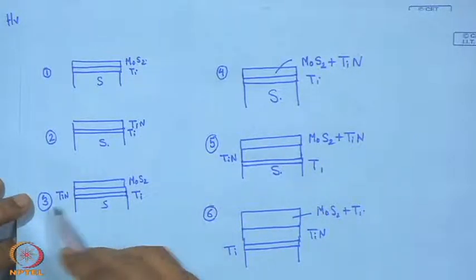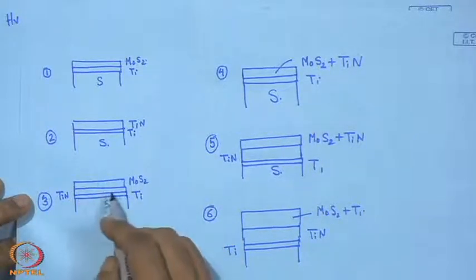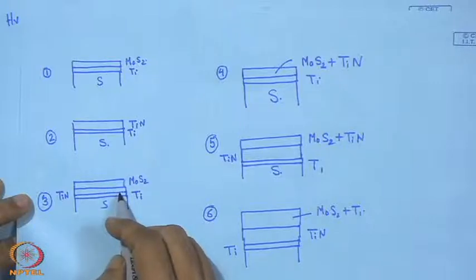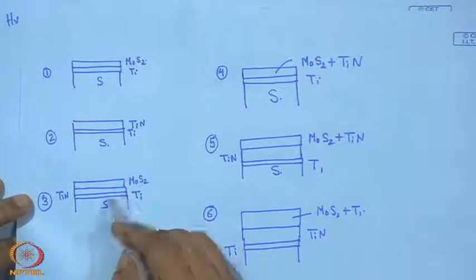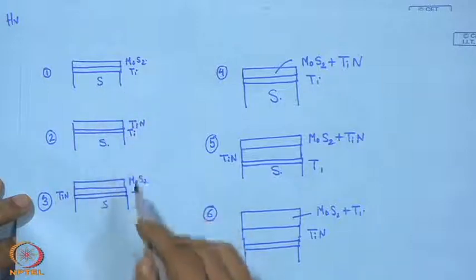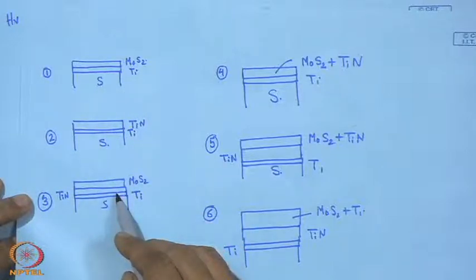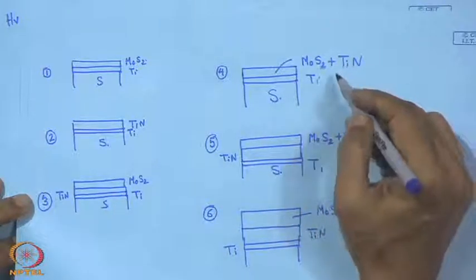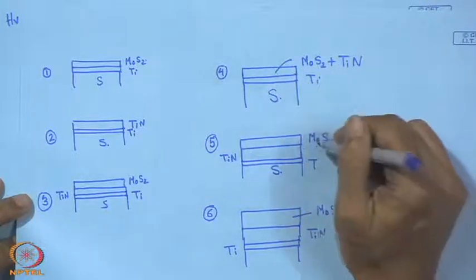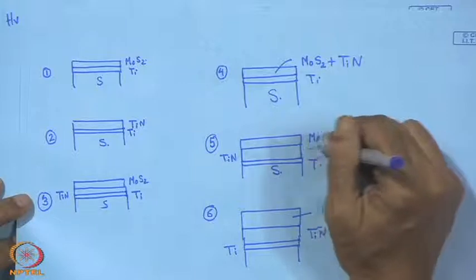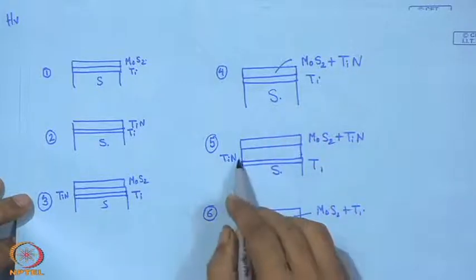However, when it is mixed with, when it is number 3 with the support of TiN, the life is actually more compared to that of this one. So, it gives a greater support. So, what we find also is that compared to this, 4, 5 is a better one, and this is because of this support of TiN.